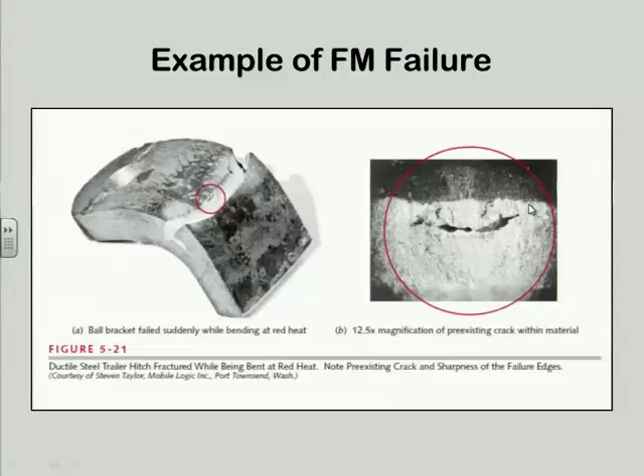It turned out after much more investigation that the culprit was, I don't know if it was that Schenectady in particular, but in one of the, I read a lot of documents from that Ship Structure Committee, and one of these studies said that a welder had erroneously struck an arc, while he's moving his torch around. He hit an arc on the deck and put a little gouge in it, a little crack. And that's where it started. And it came unzipped across the deck because of that little nick. That was the crack that started the whole thing.